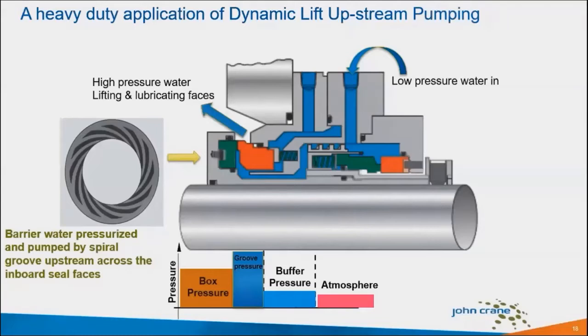As that shaft rotates, those spiral grooves create that pressure and force a tiny amount of water, probably 1/100th of the water use of a conventional seal, inboard among the pumpage. So what this addresses directly is seal face wear. Since it's non-contacting, seal face wear is virtually eliminated, even in very high pressure, up to 35 bar tailings applications. So very challenging applications have been very successfully sealed with dynamic lift upstream pumping lubrication at the inboard.